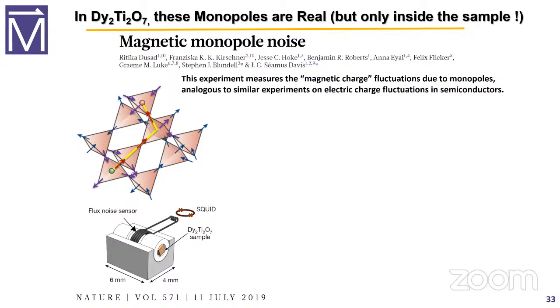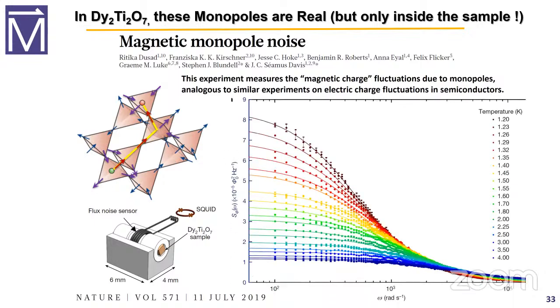So if you have a low density metal, you can actually measure the fluctuation in charge through some detector and measure the shot noise and determine that your charge is quantized. In fact, they proved that it's 1/3 charge in the fractional quantum Hall effect by measuring the fluctuations, the noise generated when you were at either integer or fractional states. So here, whenever a monopole moves through that coil, they're going to get a jump and they're going to get a series of curves. This is the noise spectrum versus frequency. These are different temperatures from 1.2 Kelvin to 4 Kelvin. There's only two fit parameters, the overall amplitude and the frequency where they roughly cross. And with those two fit parameters, you get everything else.